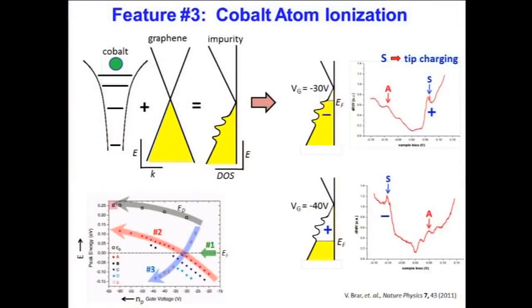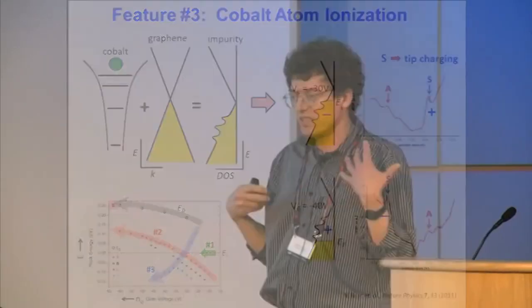For example, in this case, I have electrons in the defect state, but at this bias voltage, the STM tip is sucking the electrons out of the atom, and that's why we get this little bump. Whereas in this case, where I've already removed the charge from the atom with the gate, at this bias voltage, the STM tip is pushing electrons into the atom. And so that's why we get this little bump. So this is kind of a nice new capability that we have, which is to control the charge state of this defect using the back gate.